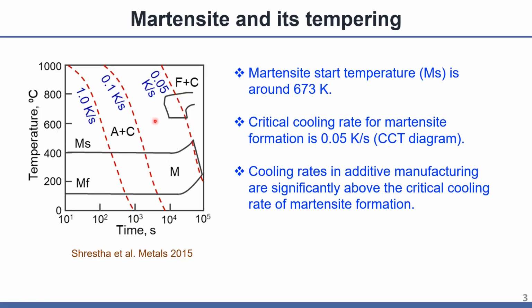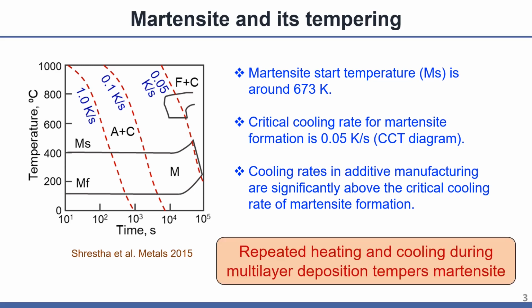The CCT diagram of grade 91 steel shows that the critical cooling rate for forming martensite is only 0.05 Kelvin per second. Cooling rates during additive manufacturing are much higher than this critical cooling rate, resulting in the formation of martensite. However, repeated heating and cooling during the deposition of multiple layers during additive manufacturing tempers martensite and significantly affects the mechanical properties of the final part.